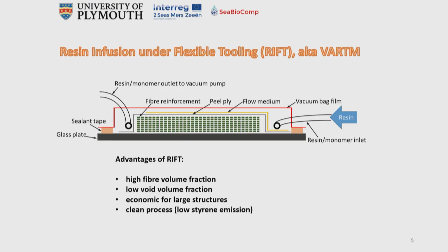The advantages of RIFT are we get a high fibre volume fraction and a low void volume fraction. It's economic for large structures, whereas trying to make a mould tool and keep it together for resin transfer moulding would be extraordinarily expensive. And it's a clean process compared to hand lamination, which has been used for some of the largest structures in the past, because it encloses the styrene in the bag, if we're trying to do it with unsaturated polyester resin.